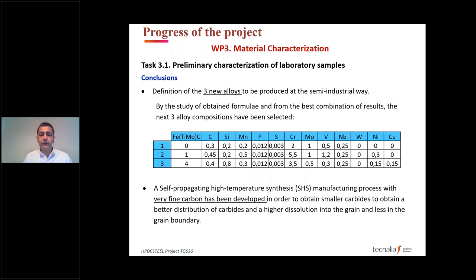We defined three alloys from these experiments. We can see that we changed the alloying percentage of master alloy from 0 till 4, and other alloying elements we also modified, from 5.5, 3.5, and 2 in the chromium, for example. But we work with a combination, perhaps in this case, for 1% of master alloy, to find which one was the best combination in chromium and other alloying elements.